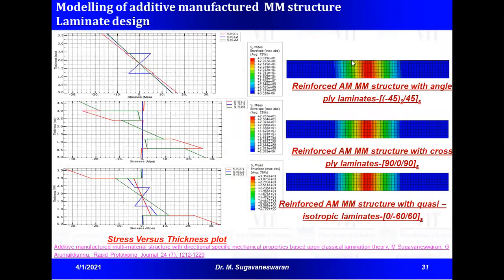As we look into the ply-wise stress behavior of the material with respect to thickness, the quasi-isotropic condition has high strength, high resistance to the bending load. This is for a bending load. So in the quasi-isotropic condition, the resistance is more at the outermost layer. These three graphs show the stress behavior across the thickness for a bending load condition. The first one is for angle ply, the second one is for cross ply, and the third one is for quasi-isotropic ply. As I have mentioned, the blue color line is for shear load. So in cross ply laminate, we do not have a coupling, so shear load is completely zero.